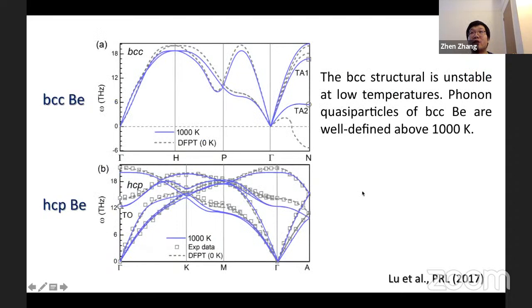Here I show the obtained anharmonic phonon dispersions at 1000 Kelvin compared with those obtained by perturbation theory for both BCC and HCP structures. The BCC structure is unstable at low temperatures. Therefore, the phonon dispersions obtained by perturbation theory show imaginary phonon frequencies. However, at 1000 Kelvin and the temperatures above, phonon quasiparticles become well-defined, and the phonon dispersion gets rid of the imaginary frequencies. The HCP structure is stable at both low temperatures and high temperatures. The anharmonic phonon spectrum of both phases were used to compute the vibrational entropy and the free energy.